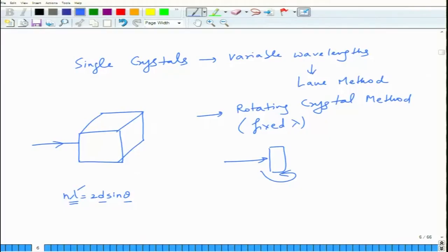And there is no guarantee that all the planes will diffract because there are very few orientations available. So, that is why you need to vary lambda. If you do not want to vary lambda, then you need to create more opportunities for theta, which means you need to rotate the crystal, okay, for diffraction to occur so that you can get some data out of it.